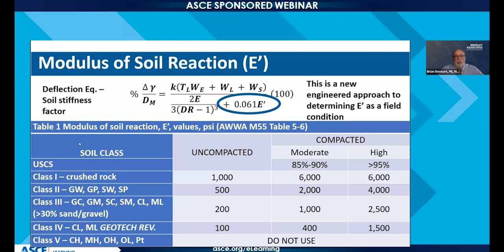Recognize, however, also in the long term, this same equation gets used for pipeline rehabilitation quite a few times. It's one of the main formulas or base formulas for 1216 for rehabilitation or putting in CIPP liners. The issue there being you have now a trench that is stabilized. You're trying to put in a CIPP liner. If the pipe is in the trench and it's happy, in other words, it hasn't failed or anything like that, you really don't have any load. All the load on your CIPP is going to be carried by the host pipe. So the E prime is dependent on what the host pipe is seeing, so not necessarily on your rehab pipe.